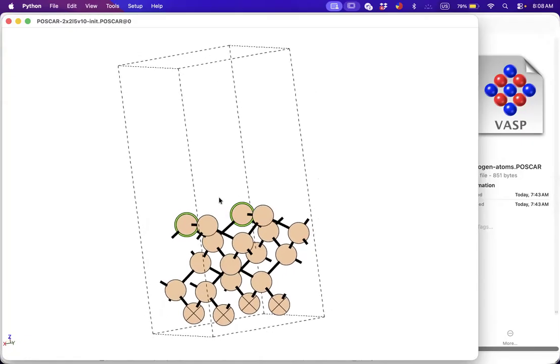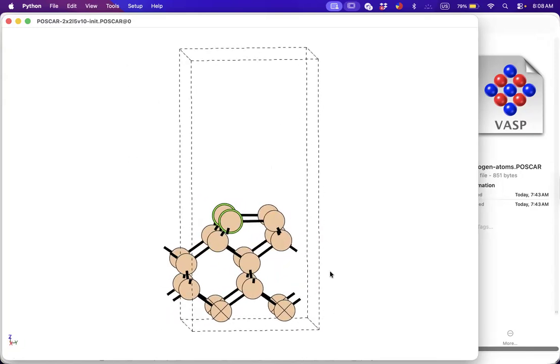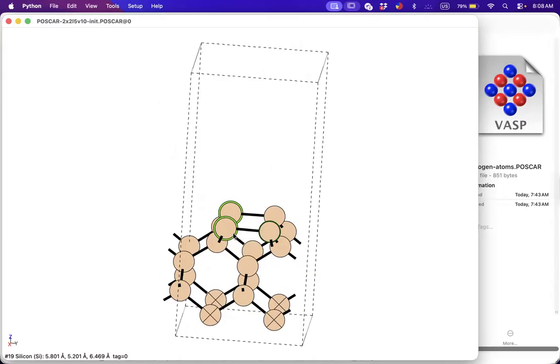For instance, the silicon distance is this, right? Look, this is 2.36. And now let's see what is the distance between these two dimers. So let's see. Look, control like this, 2.6. Okay, right? 2.6 versus 2.3. See? So it's a little bit bigger than this.